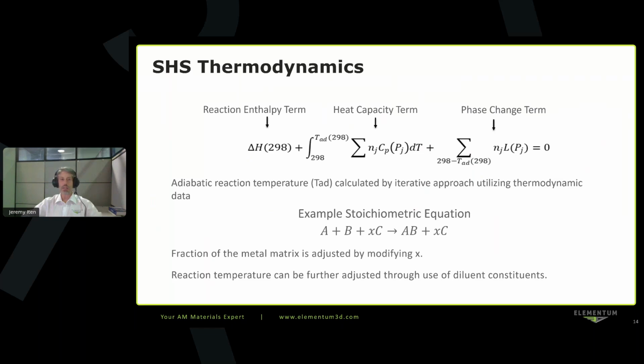So in reactive additive manufacturing, although it's not a propagating process, you still do get some temperature benefit from the reaction. So these favorable reactions will help with reducing the laser energy input you need, and help with distributing that energy. So instead of just the laser energy on the surface of the material, you can get a broader distribution of energy through the reaction to make for a more favorable processing of the material. So it can help a little bit with production speed of your material, can help with controlling your melt pool dynamics, can help with making sure that you achieve a fully dense product phase in a very favorable production speed. So you can print faster, more economical, and achieve higher densities and better products in the end, basically.